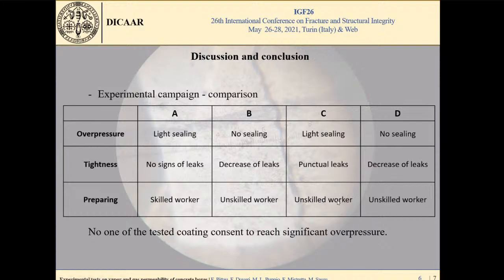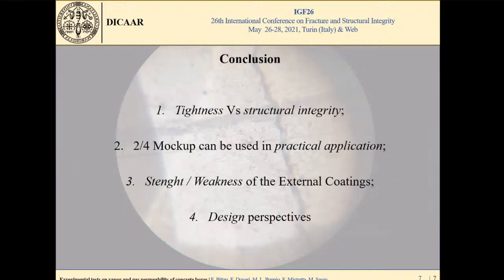So you can see, for example, that for mockup A, skilled workers are required. From the other side, unskilled worker can apply the other type of coating. As I said, the best performance in terms of tightness is relative to the specimen A and C. A and C are the best with more reduced leaks. The specimen C, in our opinion, can be suggested because of the very simple procedure of application of the external coating. No one of the specimen in this test, because of some limitation of the experimental campaign, consent to have a significant internal overpressure. But as I said, this result can be attributed to the very severe test condition.